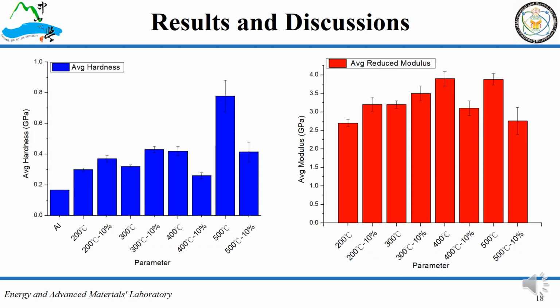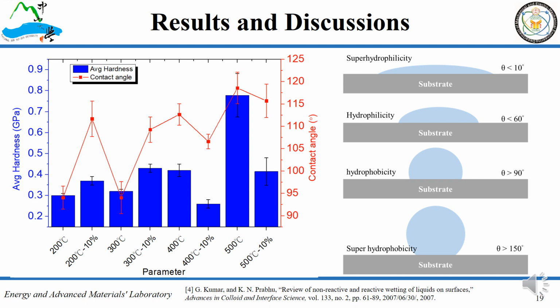This page shows the hardness and the reduced modulus of the coating layer. As shown in the left picture, the wafer coated by pure polysilicon and pyrolyzed at 500 degrees Celsius has the better hardness, and the hardness of the coating layers are all higher than aluminum. The better reduced modulus occurs at the pyrolytic temperature of 400 degrees Celsius with pure polysilicon. According to the picture, the trend of the hardness is similar to the hydrophobicity. When adding 10% AF340 and pyrolyzing at 200 and 300 degrees Celsius, the hardness and the hydrophobicity are both improved. On the other hand, the pyrolytic temperatures of 400 and 500 degrees Celsius don't show this effect. According to the definition of contact angle, the coating layers are all hydrophobic.